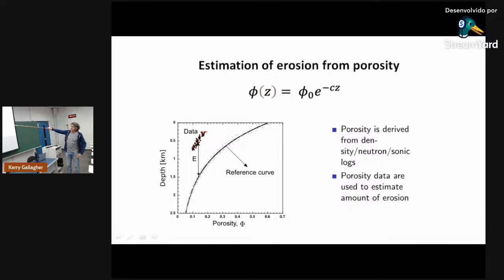So the idea of estimating erosion from porosity data is just, if we have these data, we ask how far do we have to move them down till they intersect this reference curve? Okay, so porosity data can be useful. They're not really dependent on temperature, unless we've got problem processes like dissolution or cement forming, changing porosity. If it's just mechanical compaction, it should be relatively independent of temperature.